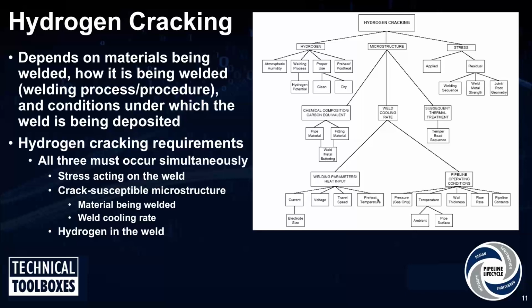Okay, so anything you could do to have that weld cool slower would allow you to have a less crack susceptible microstructure. Now again, it goes back to the welding heat input perspective. The more welding heat input you put into the weld pool, the slower that weld will cool. You need to put more heat into the weld pool because it will counteract the cooling effect of the pipeline. All right. Now the microstructure we're most worried about, we're worried about the weld metal microstructure, but the microstructure we're most worried about is in the heat affected zone. That's the area that tends to be the highest level of hardness. And that's the area that we're most worried about forming this crack susceptible microstructure. You want to go to the next slide, please?